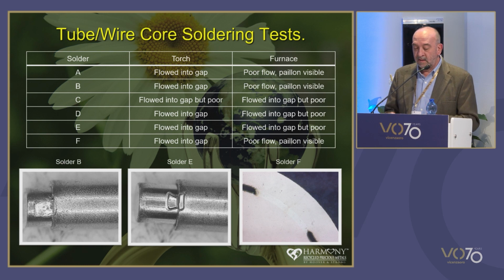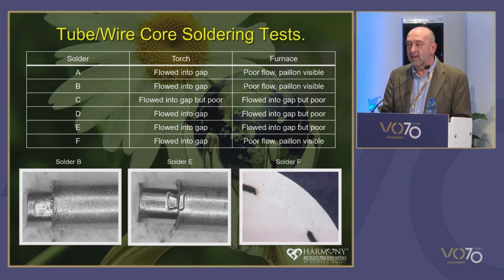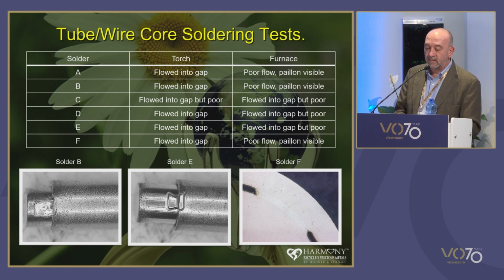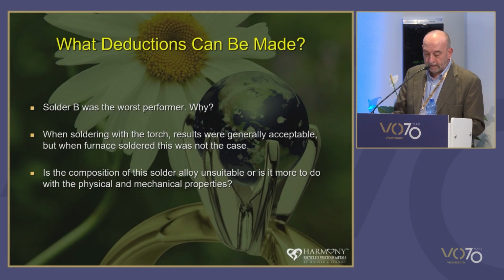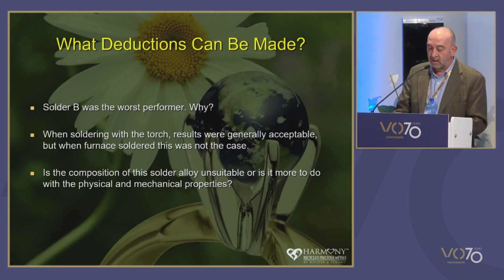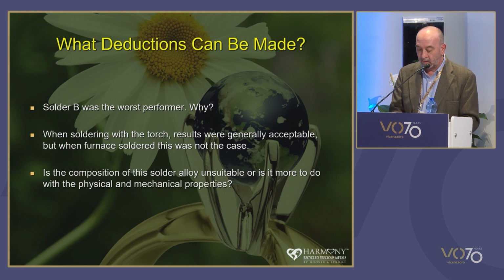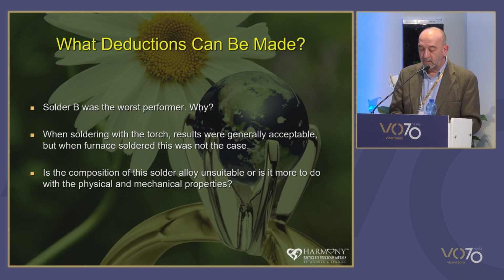So that was the end of the testing, but what did the tests show us? What deductions can a jeweler make regarding the performance of the 6 solders chosen, and can we generalize some of our deductions? Well, first of all, it's very obvious that solder B was the worst performer by far. Soldering with the torch generally produced acceptable results, but the furnace tests did not. Had poor wetting, poor flow, and the pieces didn't fully melt.